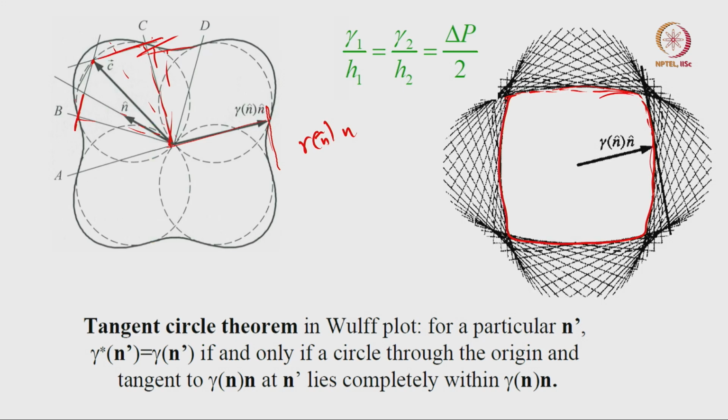So for example, this gives me the minimum shape. And how am I calculating the shape? The calculation of the shape comes by minimizing gamma dA, and that is what we said. So gamma dA is minimum, or dF equal to 0, that is essentially what this means for a given volume.